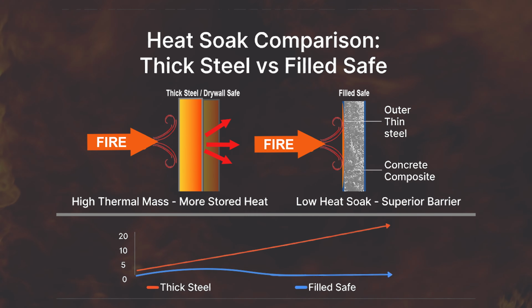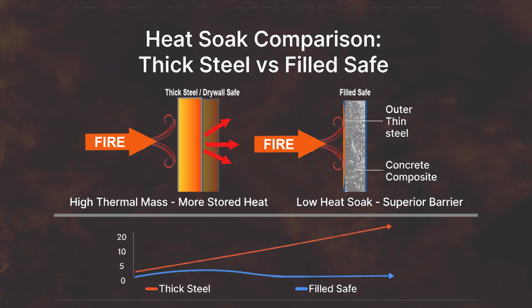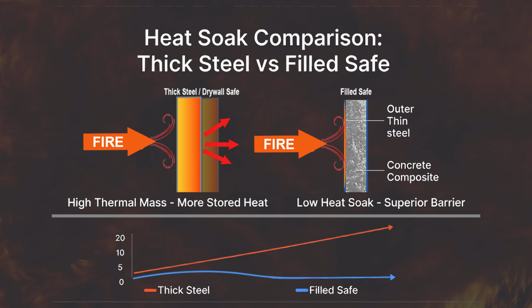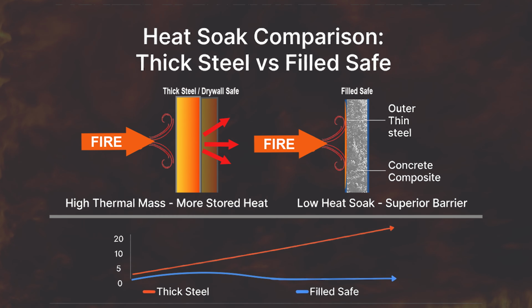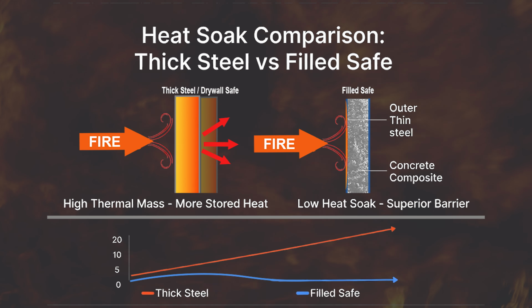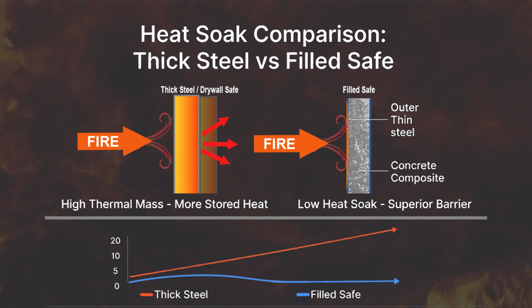A thin-walled safe, 14 to 16 gauge, has a low thermal mass. It absorbs far less heat, so once the flames have moved on, there's much less energy to cook your guns. The bottom line, in a real fire, thicker steel, heavier safes actually perform worse than lighter, thin-walled safes. This is due to the prolonged heat soak.